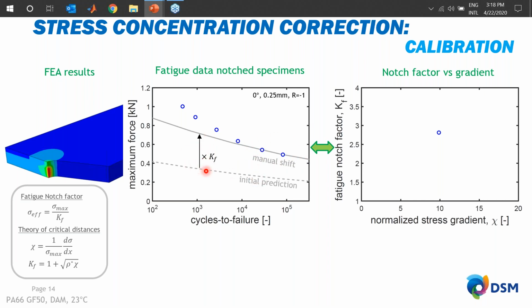But by scaling this, you compute a certain Kf value, and since you have a certain geometry, you end up with a certain normalized stress gradient. And you can plot those two against each other, as is done here on the right, where you have the fatigue notch factor versus the normalized stress gradient. We did this for a lot of different orientations and a lot of different notch radii. So of course, with a sharper radius, you increase the normalized stress gradient, and every different color represents a different orientation. And with that, we can fit this theory of critical distances.